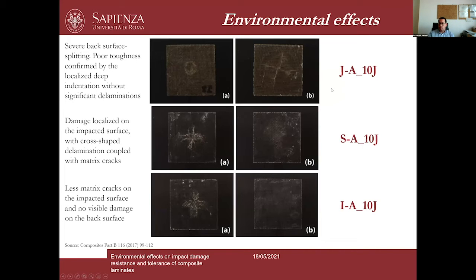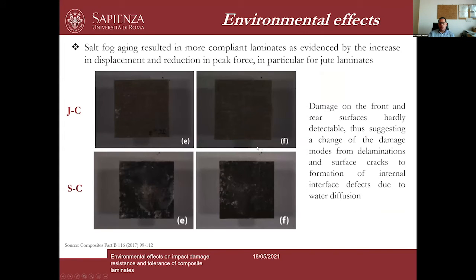But what happens when we perform exactly the same impact test on the samples which were aged? Here you have the comparison between jute and the sandwich configuration. If we compare these pictures with the previous ones, we can see that in this specific case, the damage on the front and also on the rear surfaces is hardly detectable. This suggests a change of the damage modes. In the previous case, these damage modes were mainly in the form of delamination and surface cracks. But in this case, we don't see this kind of damage; the damage was mainly concentrated inside the specimen in the form of degradation of the fiber-matrix interfacial adhesion.